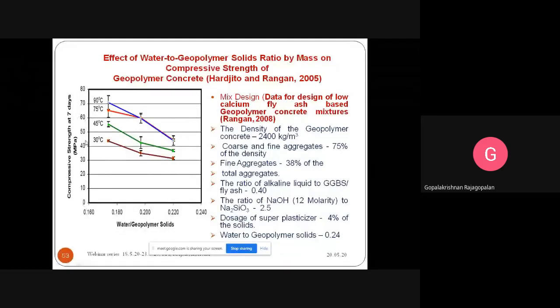Then what comparison do we need, whether we are going for heat curing at a particular 45 degree temperature, or 70 degree, or 90 degree, or you can go for 30 degree temperature. With that, we have to find out the water to geopolymer ratio. What is meant by water to geopolymer solids? Water means the water contained in the sodium silicate, plus the water used for sodium hydroxide to prepare the 12 molarity or 8 molarity or anything. Geopolymer solids means fly ash, GGBS, whatever material we are using. That ratio I have taken as 0.24 as an example for you. You can take 0.22 or 0.3, whatever it may be.